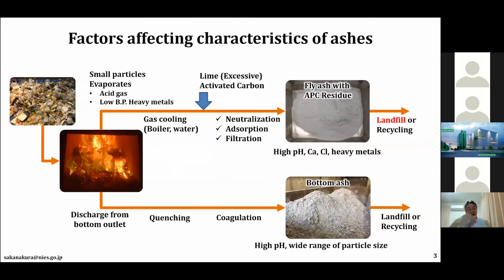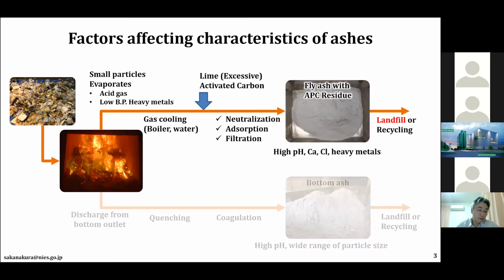So, let's consider the factors affecting the characteristics of ashes through the generation process. As is well known, after incineration of MSW, two types of ash will be obtained, fly ash and bottom ash. Today, the focus is on fly ash. Fly ash is generated because during incineration, small particles are floated along with flue gas, and the flue gas contains acidic gas and low boiling point heavy metals. After gas cooling through the boiler and water injection, some excessive lime and activated carbon will be injected in order to neutralize the acidic gas and to absorb heavy metals, such as mercury.